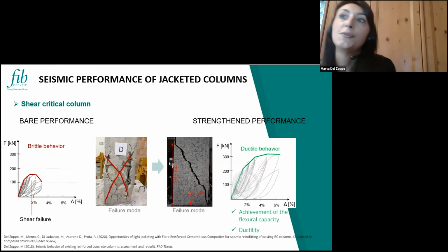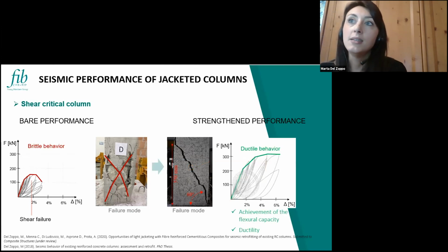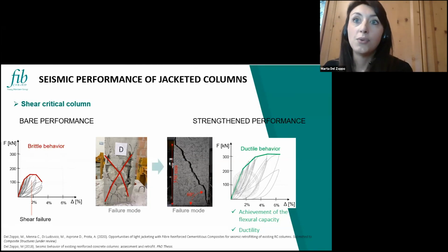And in terms of performance, if we compare the capacity curves, we can see that the jacket allowed the achievement of the flexural capacity, and so a ductile behavior for the specimen. And also in this case, of course, when we have the opening of the jacket, we observe a sudden loss of capacity. And this is clearly given by the nature of this material, which is strain softening. So this is related to the kind of material that we are using for this test.